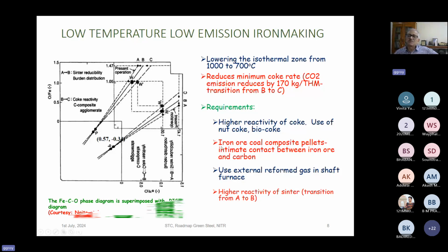It has also been found that iron ore composite pellets or briquettes can reduce the isothermal zone temperature. And you can also use some external reform gas in the shaft furnace that can help in reducing the isothermal zone temperature. Basically, if you want to carry out the FeO reduction at comparatively lower temperature, these are the possibilities. Nippon Steel has already done it, and they have demonstrated that they can reduce the carbon rate by 170 kg per ton of hot metal.